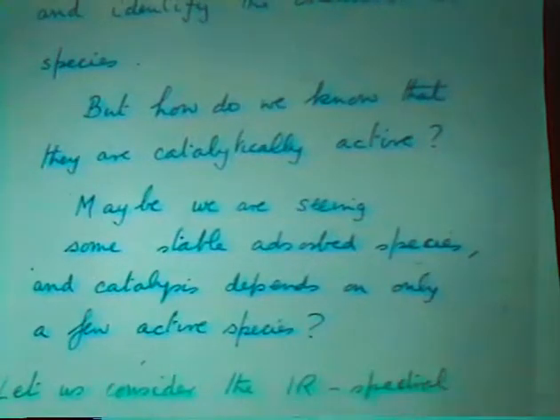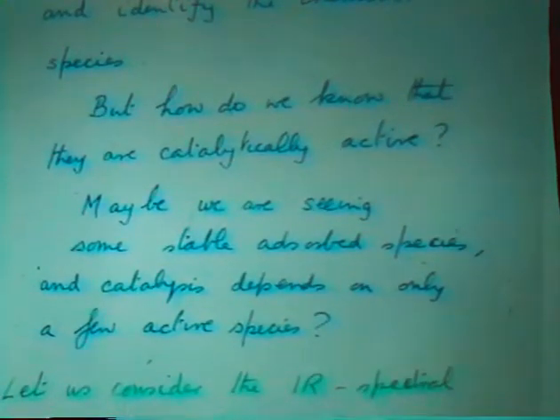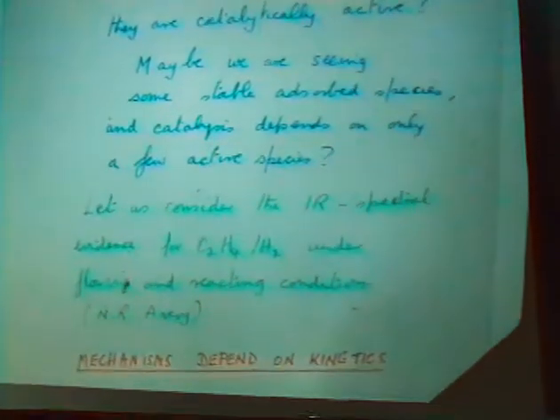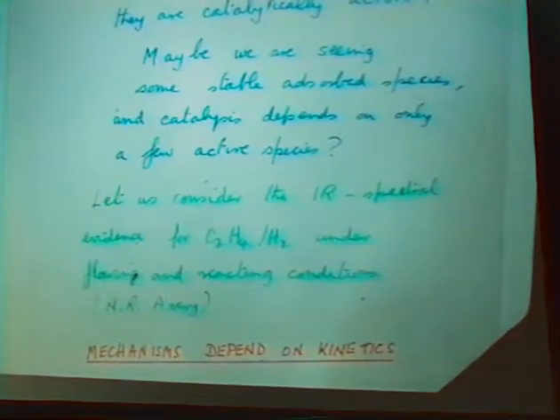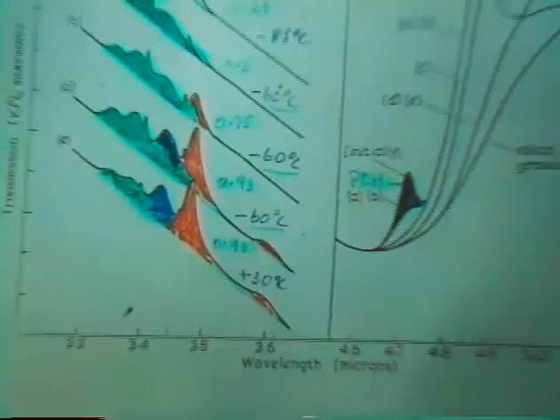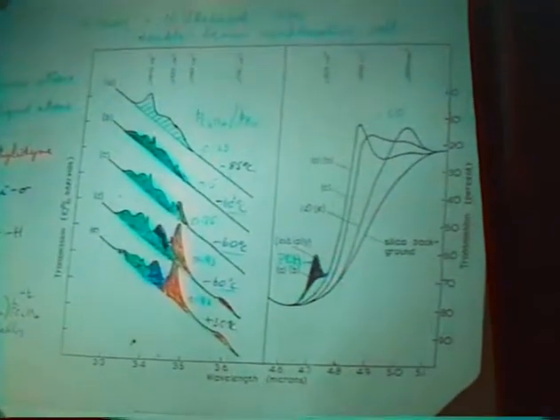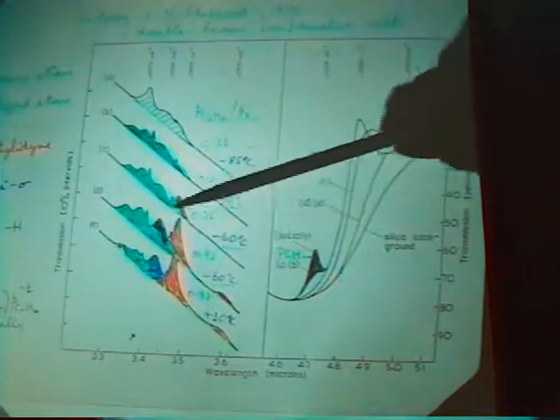Okay, so we can see and identify the chemisorbed species, but which of them are catalytically active? I think it was John Yates who produced the idea of spectator species, a rather nice description for those species which are not catalytically important. And, of course, to sort this out, you have to go into kinetics. I don't want to go into that because it would take me too long at this time, except simply to say that very early on, Neil Avery in my laboratory did some kinetic studies in which we were hoping to get the ethyl group. We didn't. What we got was the spectrum of the product, ethane. But we did show, as John Yates did later, that even when you had no ethylidyne species on the surface, the chemical reaction proceeded very happily.